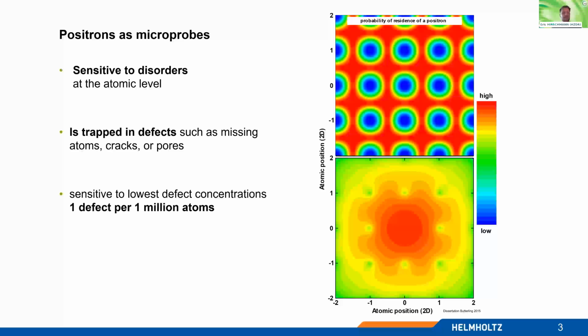And this trapping is more or less the key to investigate missing atoms, cracks, or even pores in the later phase. And due to the high sensitivity to the missing electron density in this area, the positron can detect up to 1 defect per 1 million atoms. So it's quite sensitive.